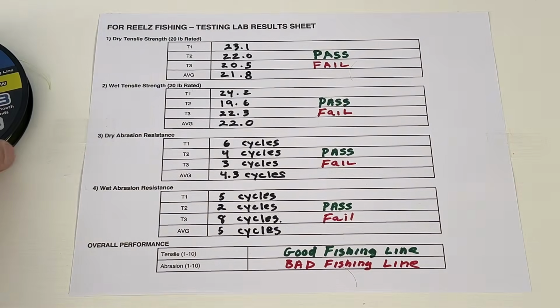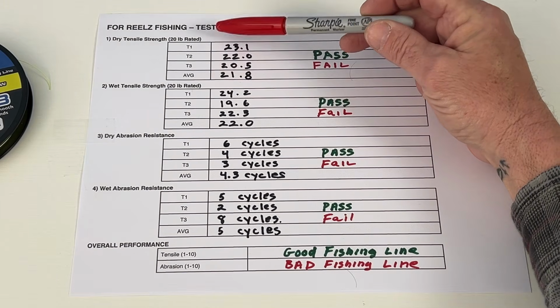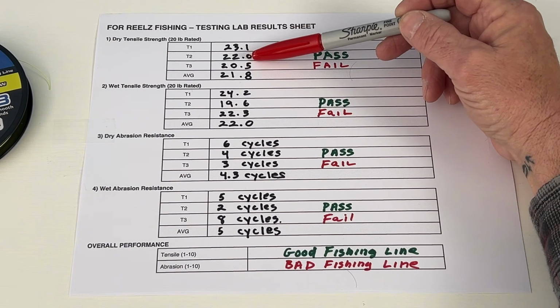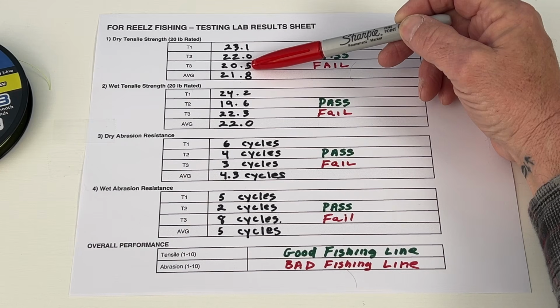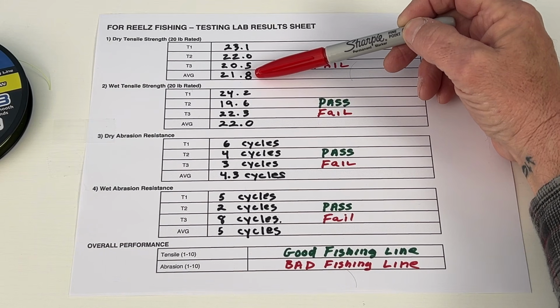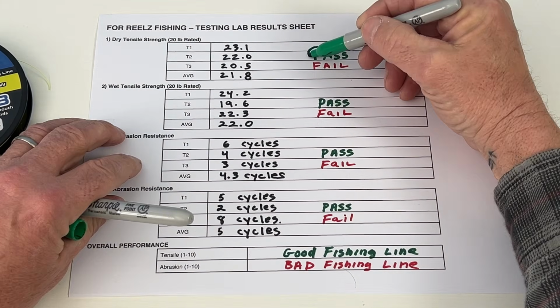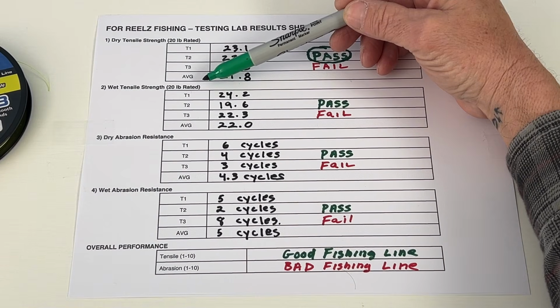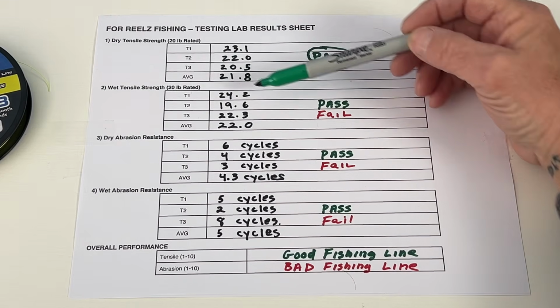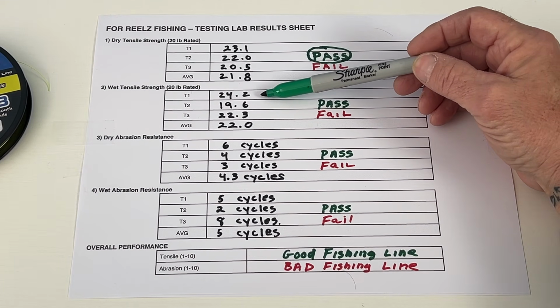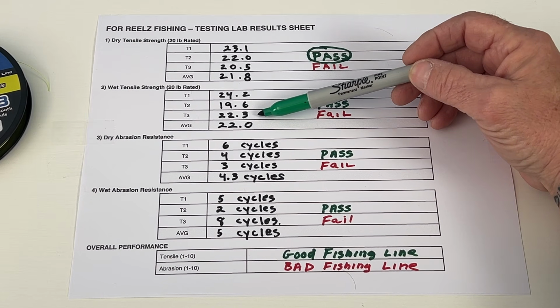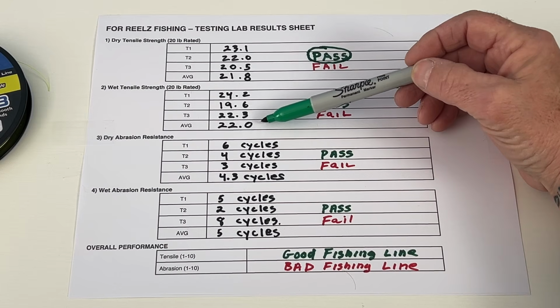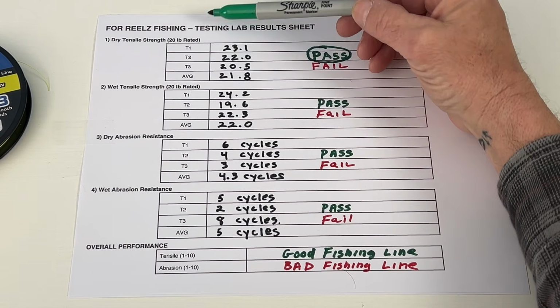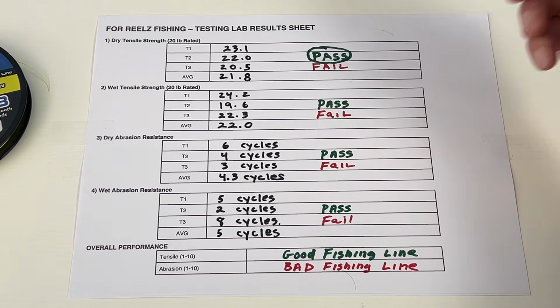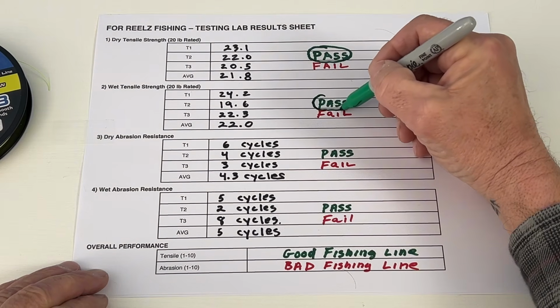Let's do a quick review on this Reaction Tackle 20-pound braided fishing line. The first 3 tests we did were the dry tensile strength of this fishing line. Test 1 was 23.1, test 2 was 22.0, and test 3 was 20.5, for an average of 21.8. So this is 20-pound braided fishing line, and this is definitely a pass. On test 2, we soaked the fishing line for over 2 hours and tested the tensile strength. The first test was 24.2, second test was 19.6, and the third test was 22.3, for an average of 22.0 tensile strength. So the average of all 3 did really good on this 20-pound braided fishing line. So we're giving that a pass.